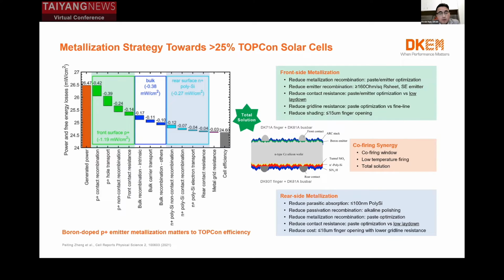On the rear side, as we always talk about, we need a thinner polysilicon layer to reduce absorption from the polysilicon layer. This also needs pastes to support it. The other is that we need to reduce passivation recombination. Mainly we use alkaline polishing. This also needs pastes to work with it. For the rear side, we still need pastes to reduce metallization recombination, and contact is also quite important. We want to highlight that for rear side metallization, we can reduce cost and achieve lower laydown. This is our main effort here.